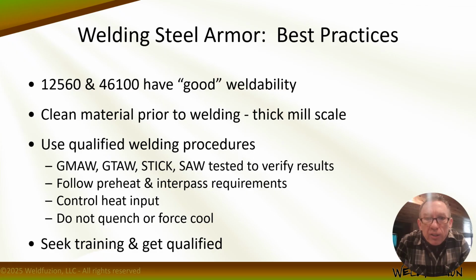Mill scale increases the chance of porosity, and I've seen it undercut way more than clean material as it burns off around the weld, especially on a horizontal fillet application. Use qualified welding procedures. You can't predict how welding will affect the material properties without testing. So develop your procedures, do the testing, and stay in the ranges. It's the only way to ensure predictable outcomes.